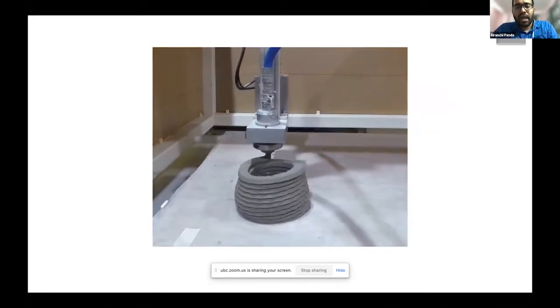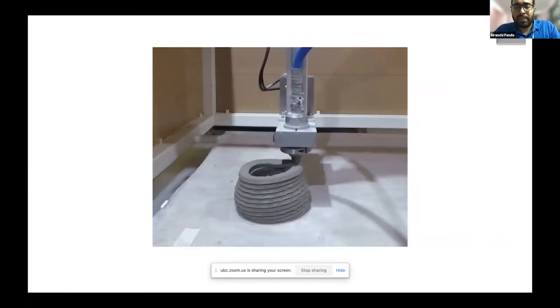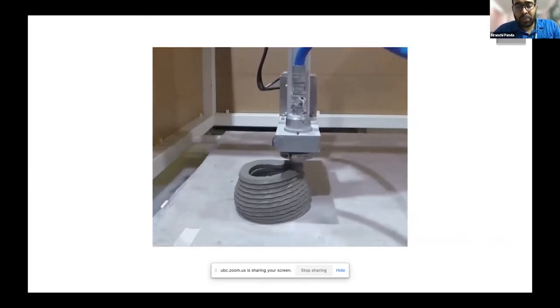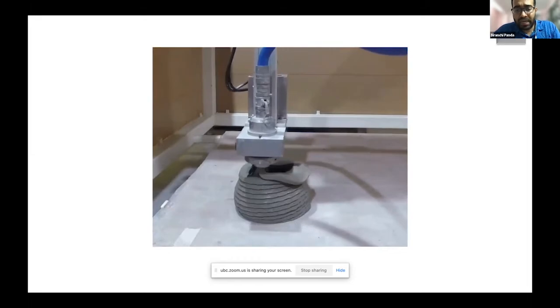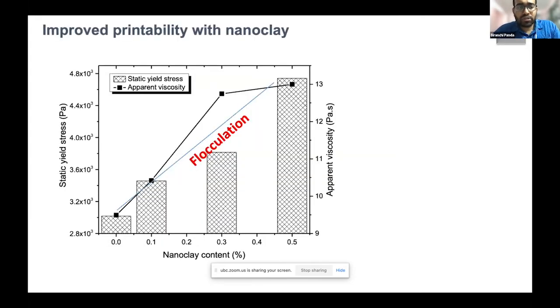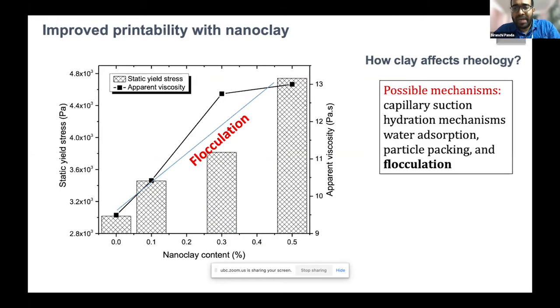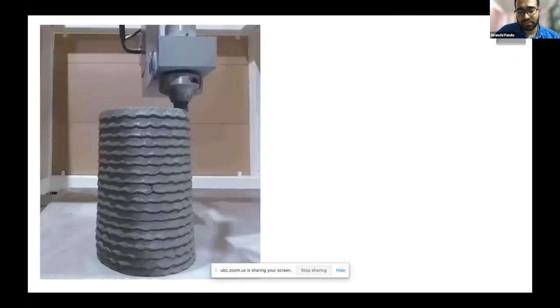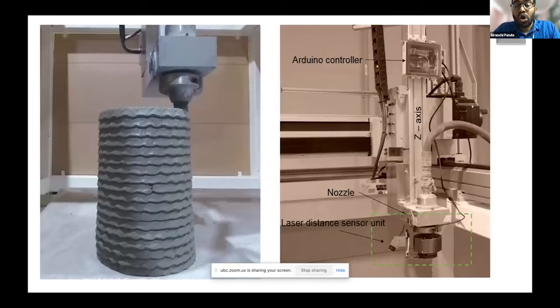So you can see that if you use a lot of fly ash in the material formulation and it is not properly designed, then you will see poor buildability after printing a few layers. In this regard, what we did is we used nano clay powders, and we see that by the flocculation mechanism we have improved the buildability. And this buildability is all from the material side. Then this is the story for the material, but we have also done some research on the machine side.